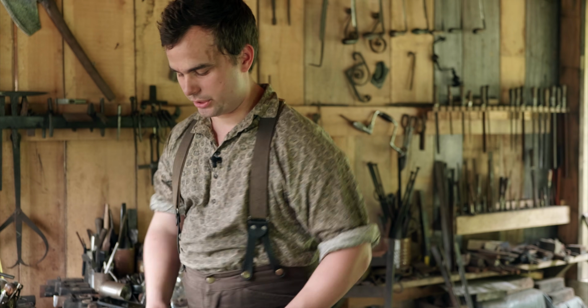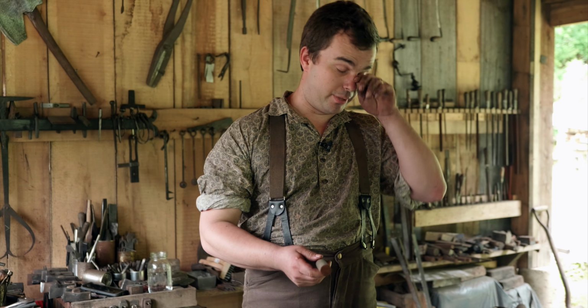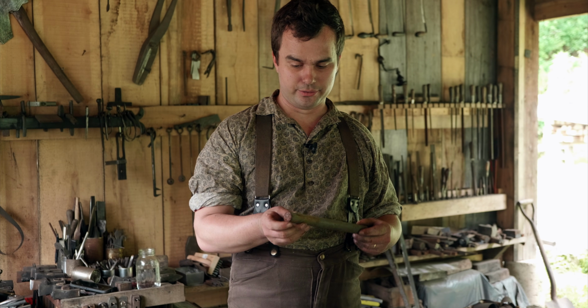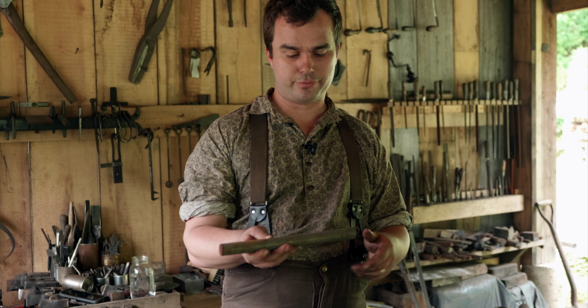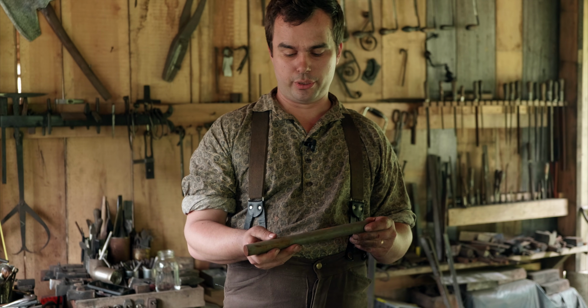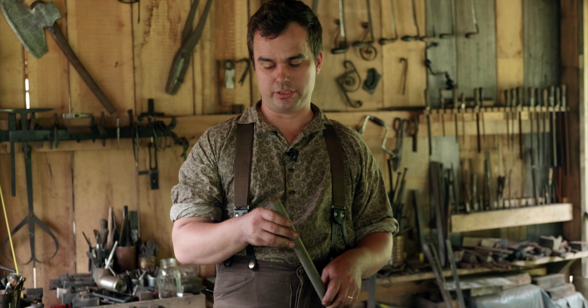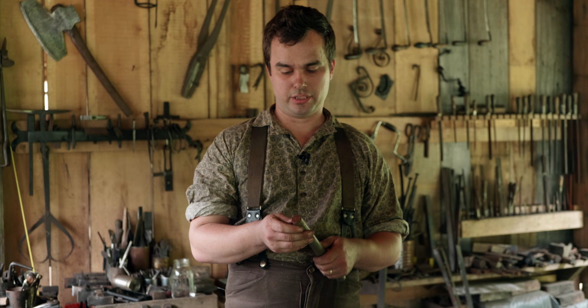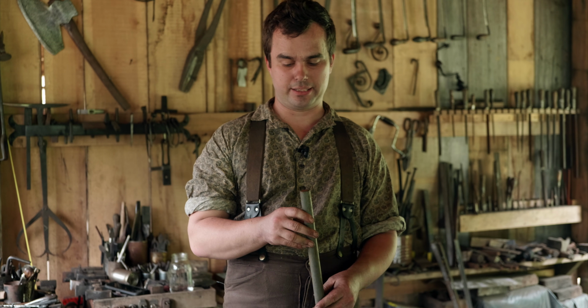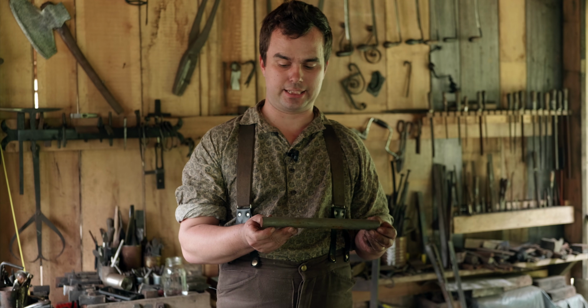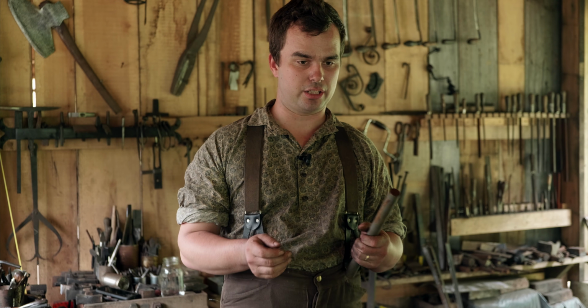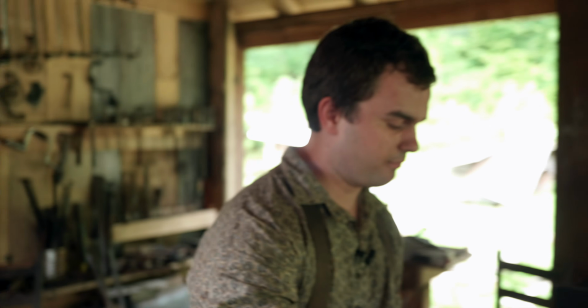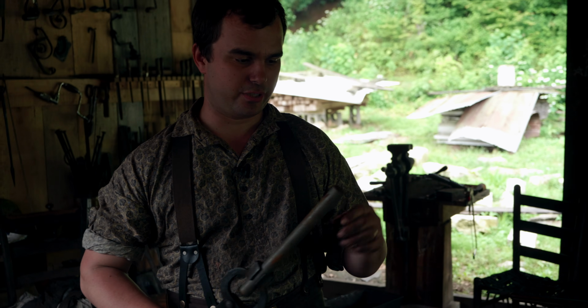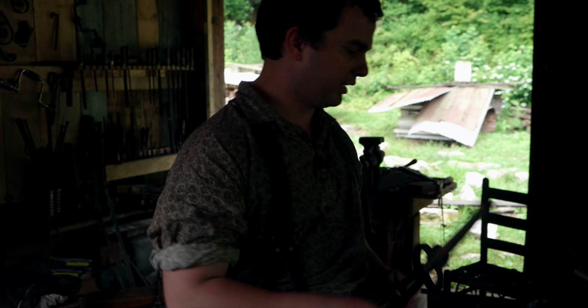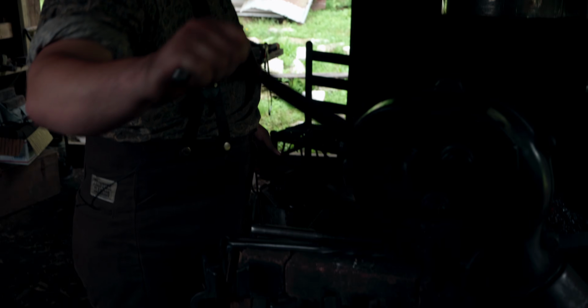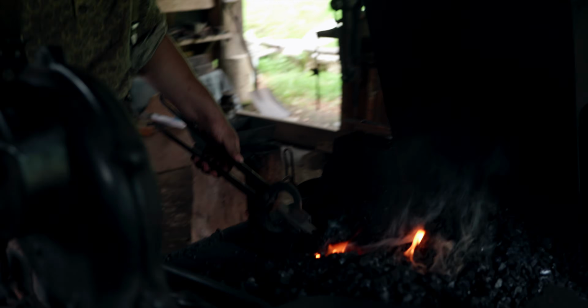So the first thing we're going to do is prep the bar of high carbon steel. I've got a piece of 1084, 1080 would be a really good steel to use, and this particular piece is round and it's about 15/16 in diameter, so just under an inch. And I'm gonna make kind of a cone shape on the end. So we're gonna heat that up, and it'll take a minute.